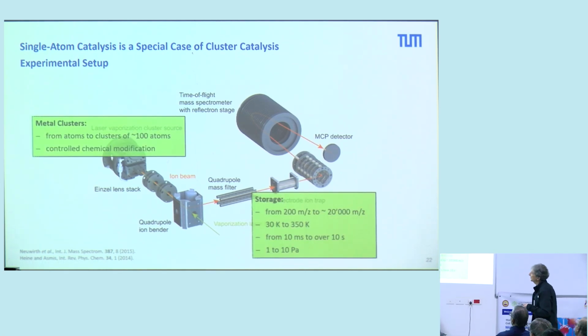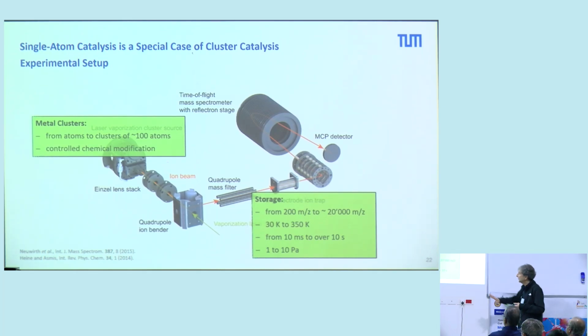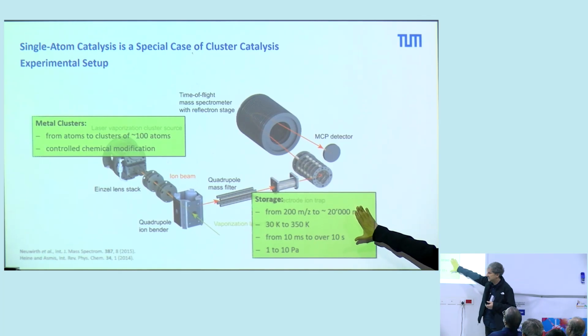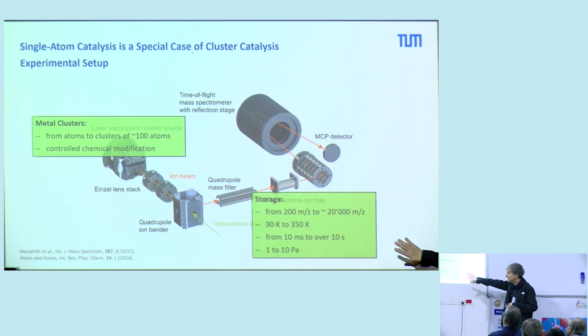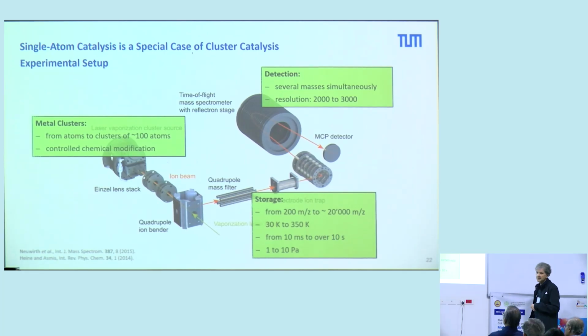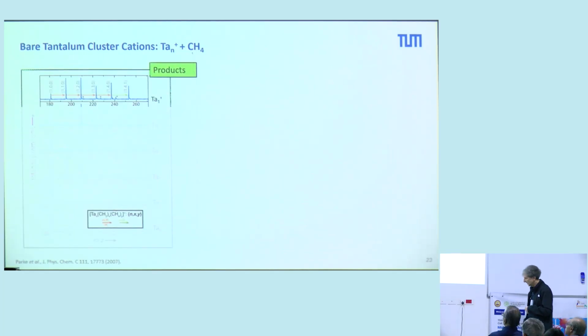I show you one example here, the characteristics of the cluster source. We can produce clusters up to about 100 atoms. We can store these in this ion trap up to 10 seconds. We can change the pressure. And of course, we can then analyze these with a time-of-flight mass spectrometer.